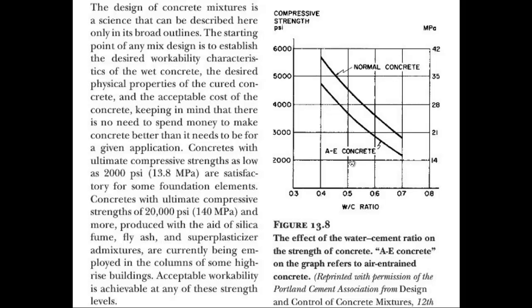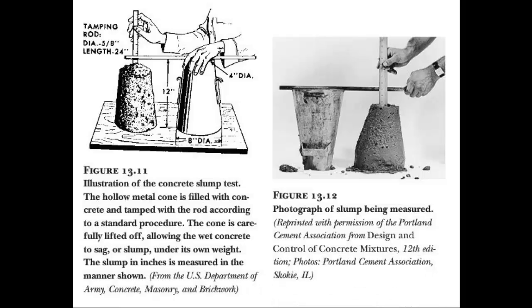At the job site as concrete is being poured, we do a slump test. An inverted cone is filled with concrete, tapped down to remove air bubbles, then the cone is pulled off and the distance the concrete slumps is measured. Specifications call for a specific slump in inches — for example, a maximum 2.5-inch or 4-inch slump. A technician on site performs this test and also takes samples to be tested for PSI strength.